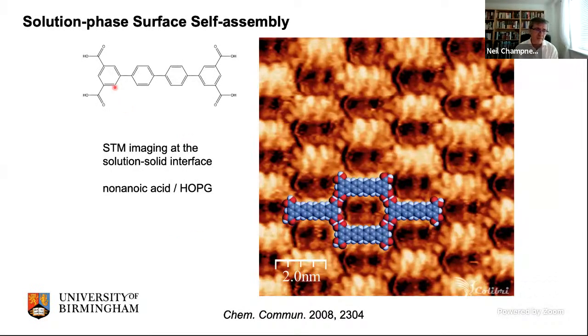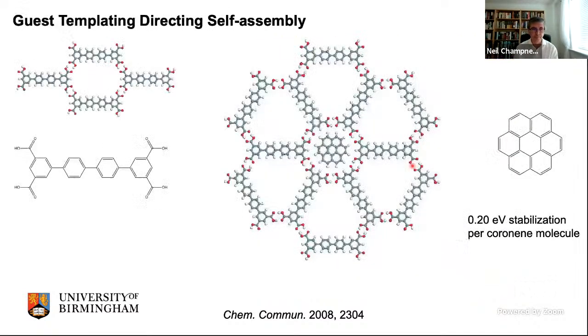This is a quaterphenyl tetracarboxylic acid. We can deposit this onto a surface, in this case graphite. And this is actually imaged under solution, so under nonanoic acid, which is just an STM solvent. It has the right conductivity properties for STM. And you form carboxylic acid dimers, as you can see here. Each of these features is an individual molecule. So you can see that.